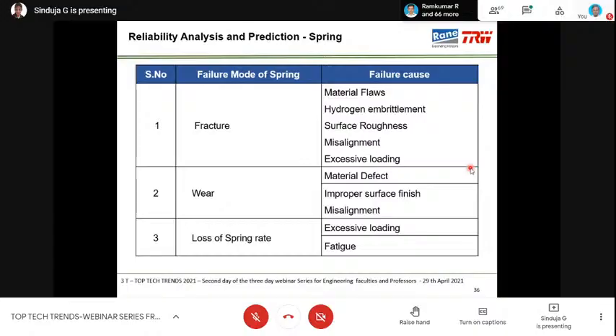The fracture itself could be because of a material defect, and you can recall this could cause a decreasing failure rate. It could be a starting problem, like a decreasing failure rate. You can recall that a raw material problem will typically result in a decreasing failure rate in the early part of the bathtub curve. Now hydrogen embrittlement is again a process issue. We had a classical example of this in some of our fasteners, because when the part is heat treated, the hydrogen de-embrittlement process has to be followed so that cracks don't happen on the part.